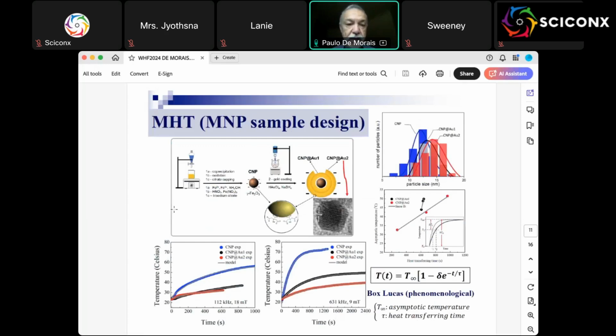Okay, when we perform magnetic hyperthermia with the samples, we can, for instance, look at the response, the temperature versus time curve. On the left-hand side, lower part of my slide, I can show you the response when we are using a 112 kilohertz AC magnetic field at an amplitude of 18 millitesla. And then you can see the response of the 3 different samples. The blue data shows the typical trend of the temperature, but you can see that the asymptotic temperature goes higher than 50 C, which means if you operate this in a standard magnetic hyperthermia treatment, you are going to perform necrosis.